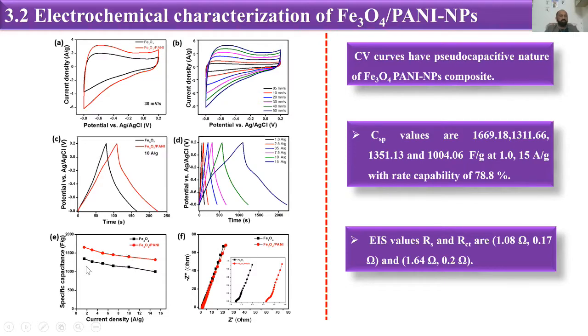And then we have calculated the capacitance for Fe3O4 and Fe3O4 Pani nanoparticles. And we have done EIS again, we have done the EIS curves, and we have calculated the Rs and Rct for our sample.